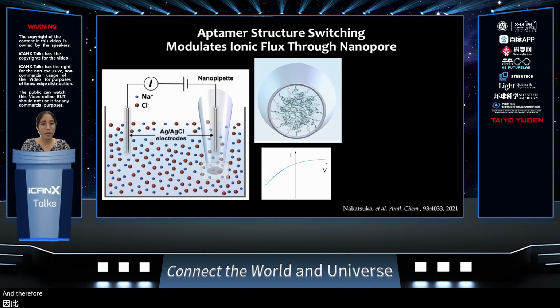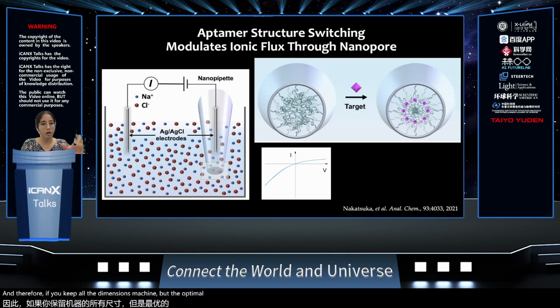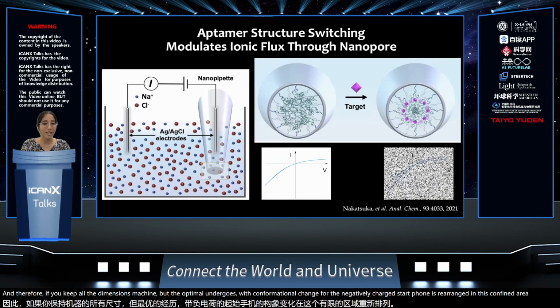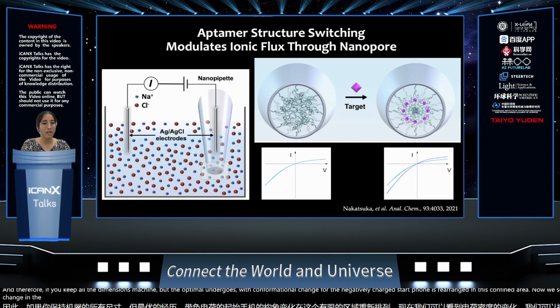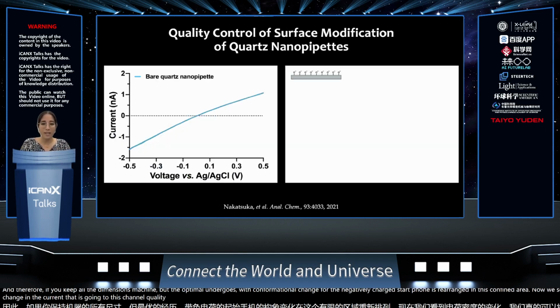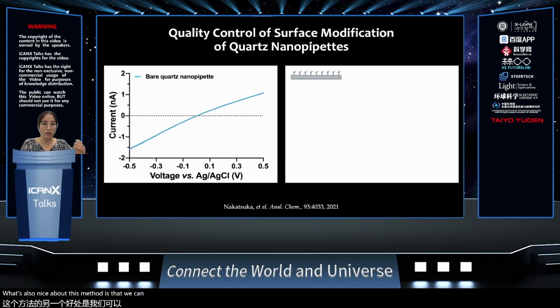And therefore, if we keep all the dimensions the same, but the aptamer undergoes this conformational change where the negatively charged backbone is rearranged in this confined area, now we see changes in the charge density, and we can really transduce this as a change in the current that is going through this nanopore. What's also nice about this method is that we can really track this difference in the surface charge density at different states of the surface chemistry.